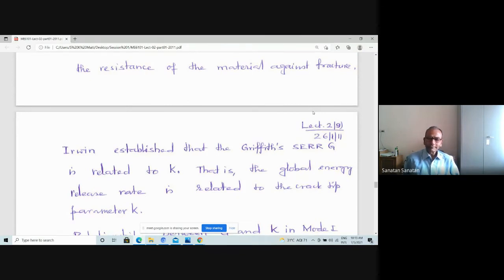The person who really developed this stress, K, is called the stress intensity factor. The stress intensity factor based approach was given, that this K is an important parameter for failure. When you increase the loading, the K parameter is related to the loading. So as you increase the loading, stresses also increase, and from common sense you can say that a typical level of loading is leading to fracture, and therefore a typical value of this K parameter is reached at the point of failure.